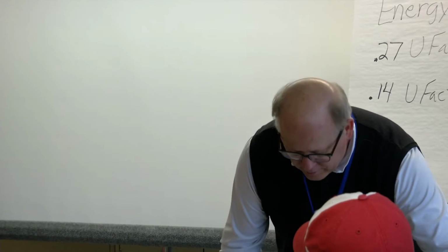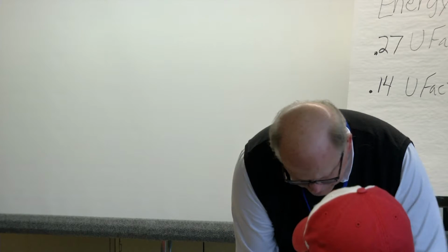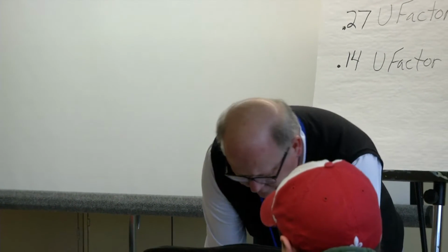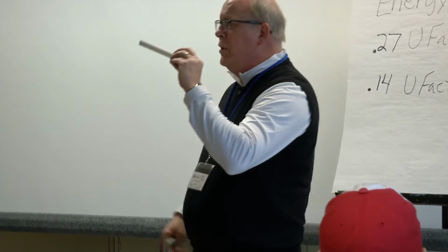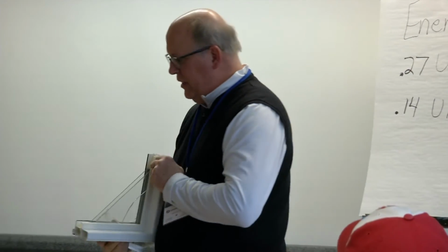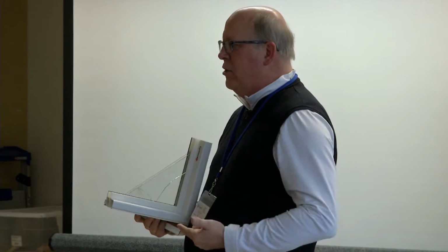So let's talk about spacers, because this is important. In between the panes of glass, what's holding it apart can be very, very important to the overall energy efficiency of your window. So if you have an old-fashioned window that has an aluminum spacer in it, aluminum, just like this stainless steel spacer, will conduct a lot of heat and cold across it, so the cold from the outside comes right across to the inside, creates a cold edge, creates condensation, because warm air comes over, gets cooled, cold air can't hold as much moisture as warm, boom, puts it right there on the edge, rot, mold, all the problems, all the issues.